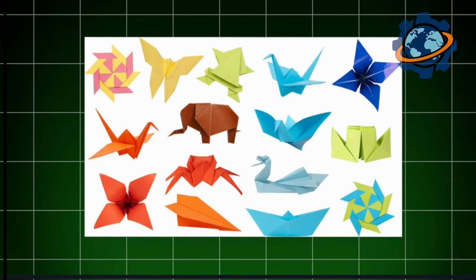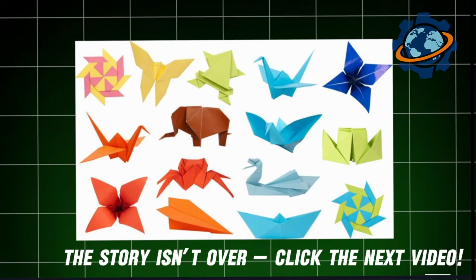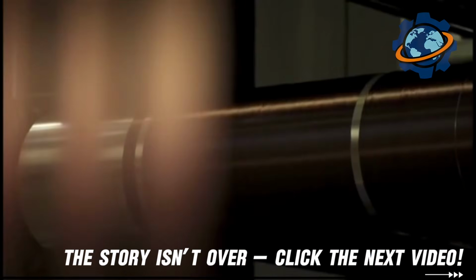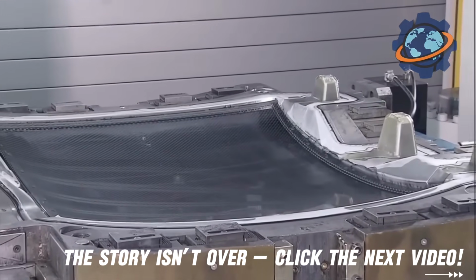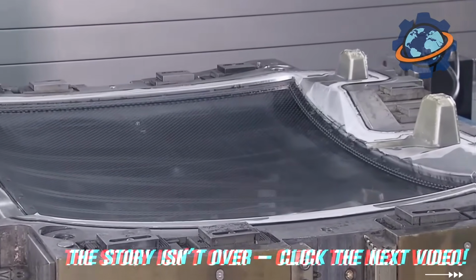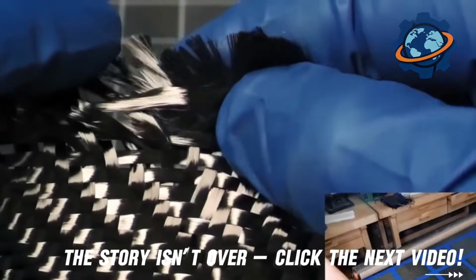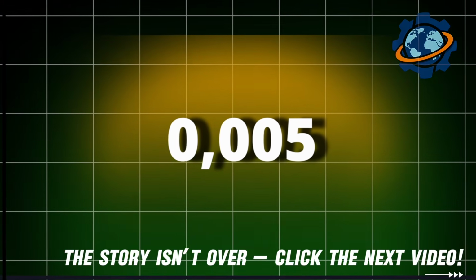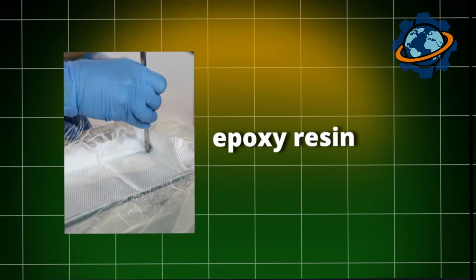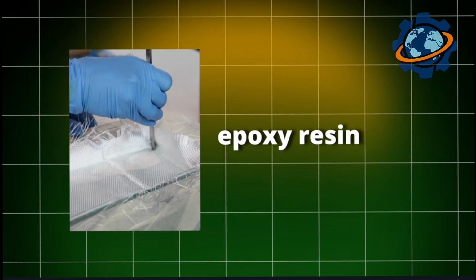Picture this: laying up carbon composite resembles origami, with materials costing $300 per pound. Technicians cut fabric patterns, stacking layers in precise orientations. Each ply orientation, 0 degrees, 45 degrees, 90 degrees, contributes specific strength characteristics. A typical aerospace laminate contains 40 plies, each 0.005 inches thick, creating structures 0.2 inches thick, yet lighter than equivalent aluminum. Between each ply, workers brush epoxy resin, ensuring complete fiber wetting.